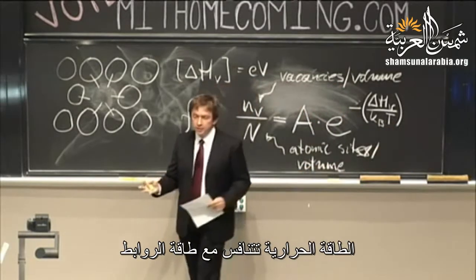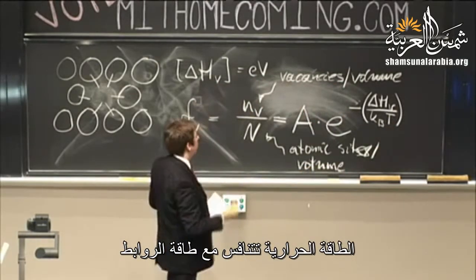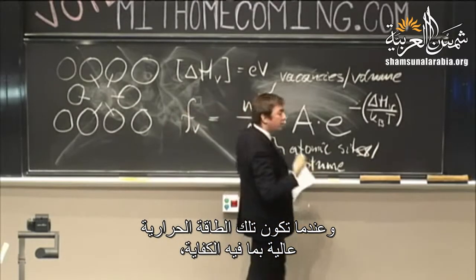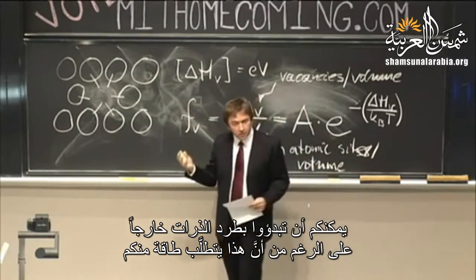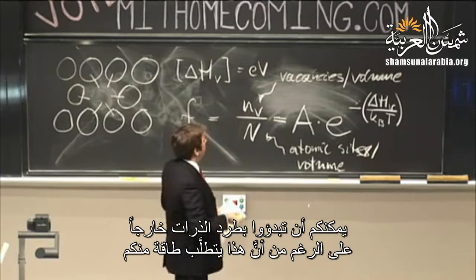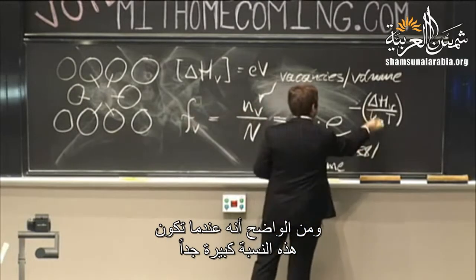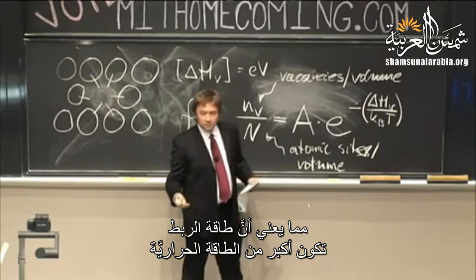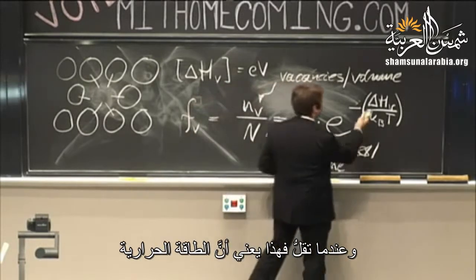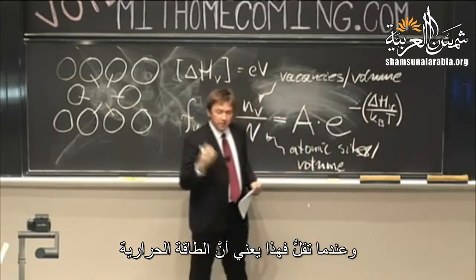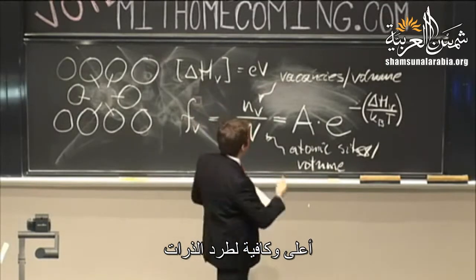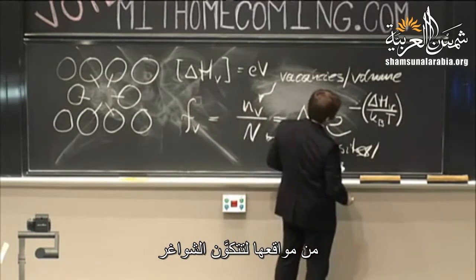And the thermal energy is competing with that bonding energy. And when that thermal energy is high enough, you can actually start knocking atoms out, despite the fact that it costs you some energy. And obviously, when this ratio is very large, that means that the bonding predominates. And when it gets smaller, that means the thermal energy is more and more sufficient to actually knock atoms out of their positions and cause there to be vacancies.